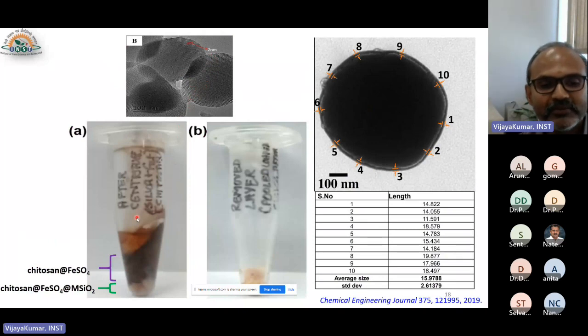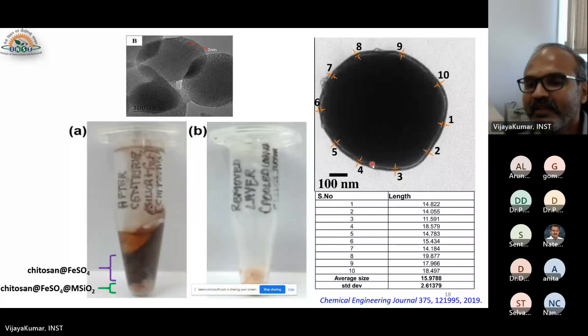And then you keep it on this chitosan gel. This is a gel matrix that we have optimized, over which you keep the mesoporous silica loaded with FeSO4, and you spin it. Once you spin it, you get a lower dirty white color and then a dark brown color, and then the gel remaining. So this is the FeSO4 that is not loaded into the mesoporous silica, and this dirty one, when you stain it and see it in the TEM, you can find a nice 13 to 16 nanometer coating of chitosan around it and loaded with FeSO4 silica.